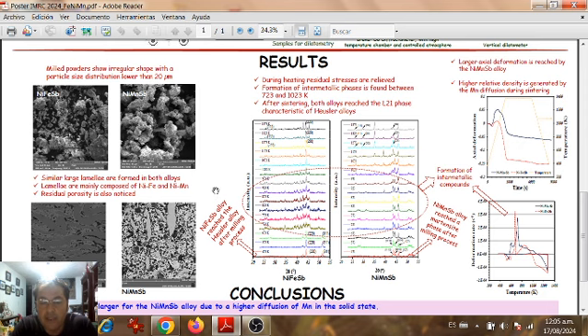When we are using nickel iron antimonium, we obtain the Heusler alloy after the milling process. Instead, when we are using the nickel manganese antimonide alloy, we reach a martensite phase after the milling process. During the heating to reach the sintering temperature, which was 1100 degrees, we notice that different changes are occurring in the crystallographic phases.